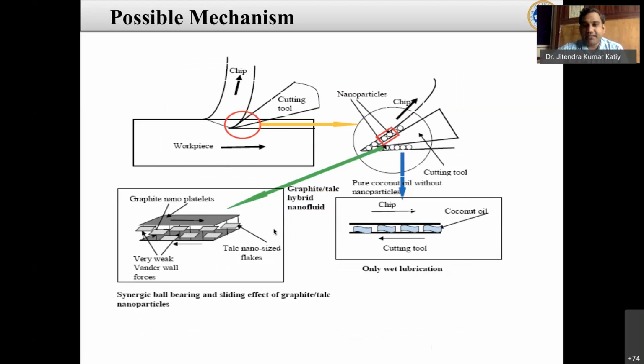So that is the observation from the tribological characteristics. And what is the possible mechanism which I proposed in this paper? The nanoparticles come in between the tool and chip interface. Because of that, the surface roughness is also improved, and the fluid can easily move away from the workpiece surface, take the heat from the chip and remove it, and reduce the forces because there is no direct contact between the chip and tool, with the nanoparticles in between. So that is the possible mechanism. Because of that, the life of the tool is also improved, you can reduce the cutting forces at the interface, and you can get a better surface finish in that particular turning operation.